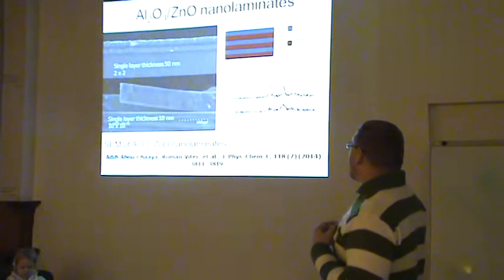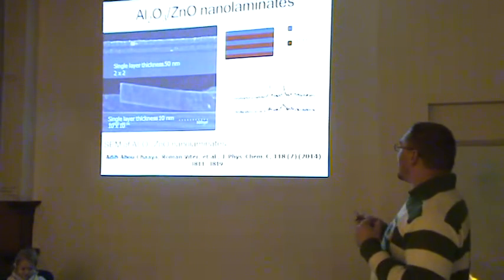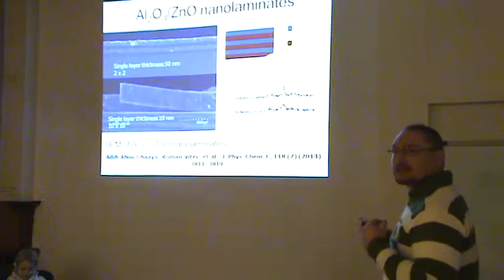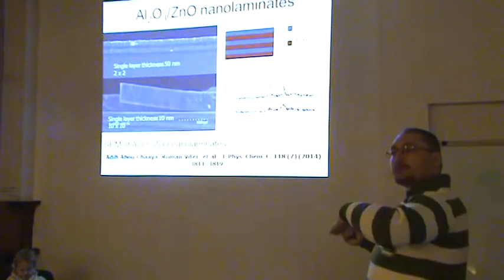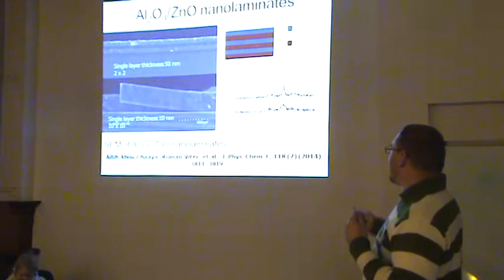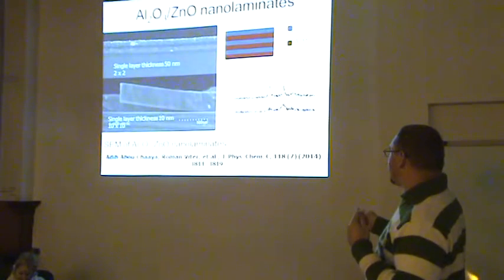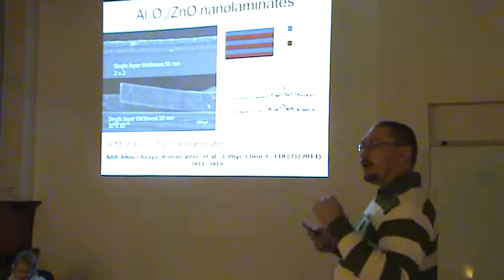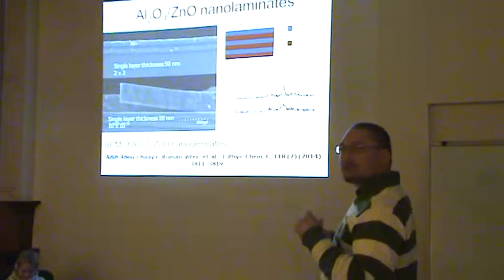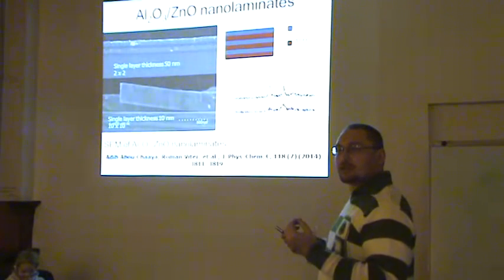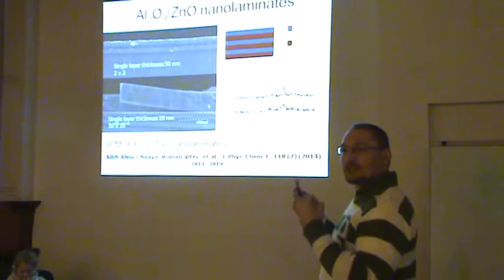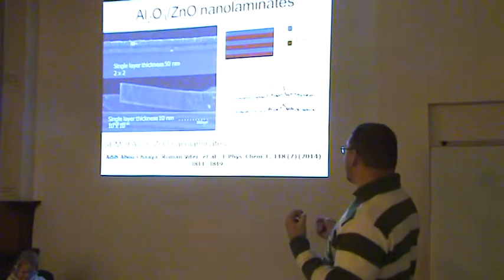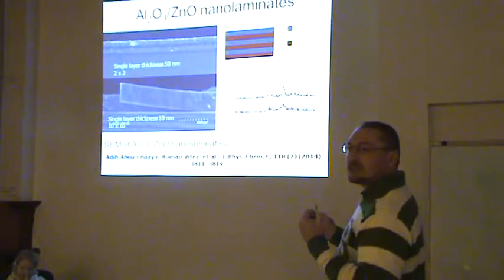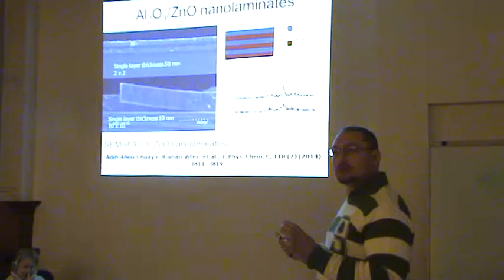And here we analyzed what we deposited using this technique. And these peaks show that we have zinc oxide. We didn't see aluminum trioxide because it was amorphous. So no crystalline structure was inside. Therefore, in X-ray diffraction, no peaks related to aluminum trioxide.